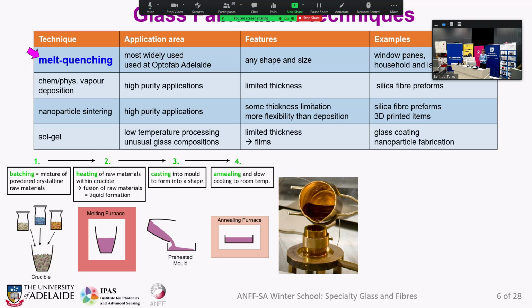Then you can cast the molten glass into a mold, as shown in the photograph. And now you can imagine the shape depends on the size of your mold, and of course also on the volume of your glass. At the laboratory, we make small volumes in the order of 100, 300 milliliters, but you can imagine if you want to make a window pane, then the volume of your glass goes into the tons.